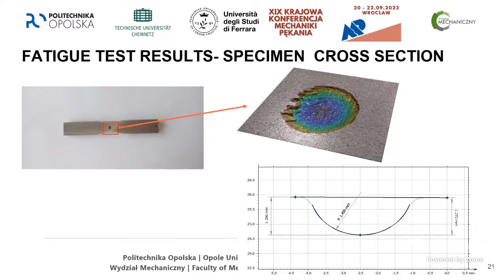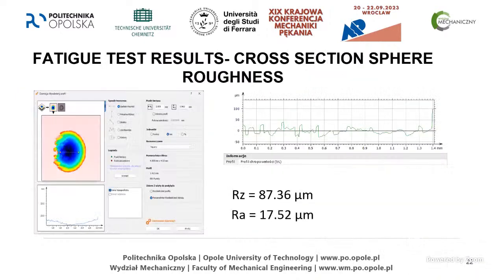As you can see in this specimen, maybe you cannot see, but I didn't highlight it, in the area where we had those artifacts, we don't see any effect. So there is no additional element where during a CT scan we would have this area that was on the image. So maybe while we were cutting this, it was melted or something else happened, but we cannot see it after the cross-section cut. We also performed a cross-section sphere roughness examination. As you can see, it was roughly 17.5 micrometers, right? We also analyzed the surface.